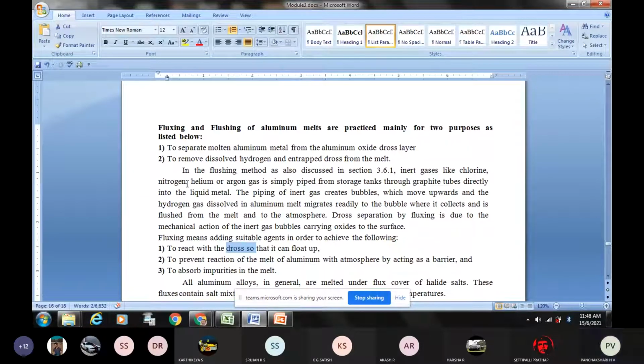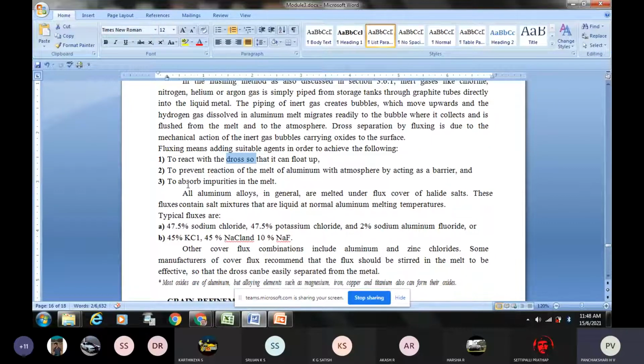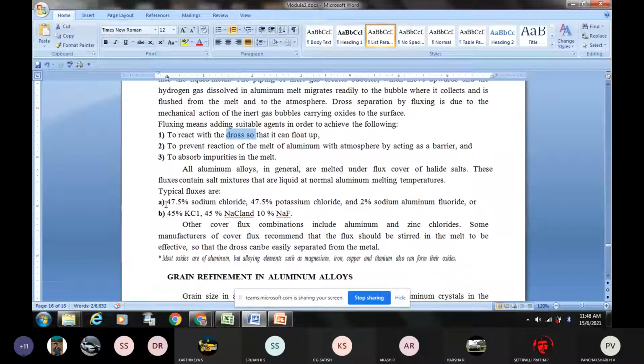The typical flux combinations are also given; you can see the combinations of fluxes. A flux being used in the aluminum melt is 47.5% sodium chloride, 47.5% potassium chloride and 2% sodium aluminum fluoride. The second option is 45% KCl, potassium chloride, 45% NaCl and 10% NaF, sodium fluoride. These are some of the fluxes used when we are melting aluminum and producing aluminum castings. These fluxes are very essential for removing the dissolved hydrogen gas and the impurities.